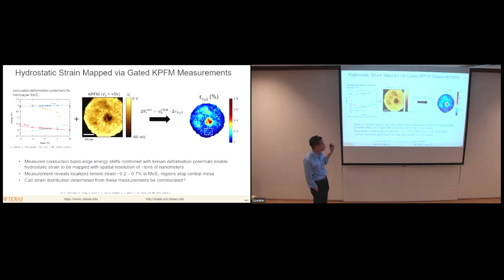Now, what we can then do is take that variation in the band edge energy and translate that to strain, because it's known how the band edge energy depends on the strain for these materials, right? So these are the deformation potentials that have been calculated for all these materials. They turn out to be dominated by the hydrostatic component of strain, which is the change in the volume of the unit cell, okay? And so since it's known what the energy of the band edge is as a function of the strain, then we can pretty directly go from this map of the band edge energy to a corresponding map of the hydrostatic strain, all right? And we can get this with spatial resolution on the order of tens of nanometers, okay?